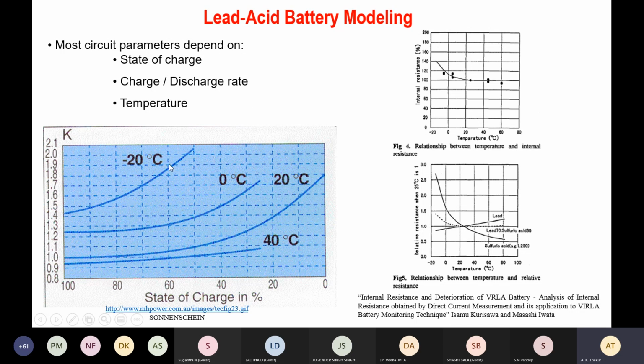Here is a clear effect of temperature in a commercial cell. At 40 degree, at 20 degree, it performs very well. If we increase temperature, as I mentioned, electrolyte thinning and electrolyte water evaporation occurs. As a consequence, performance dies down. And when we reduce temperature, then also its performance dies down, because water freezing is the natural consequence at zero itself for aqueous electrolyte. And if some anti-freezing agent is given in the design, then it may not freeze sharp at 0 degree, but there would be a drastic drop in performance and current delivery rate.